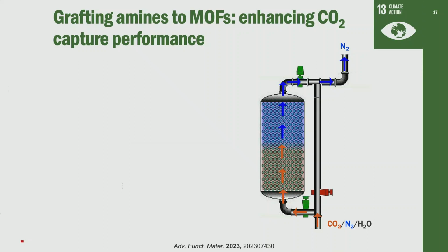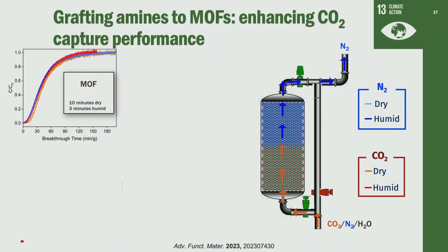The material will grab the CO2, and the first thing that comes out of the column is nitrogen. So we watch when the nitrogen comes out, then we watch when the CO2 comes out later. The difference is referred to as our breakthrough time, the difference in those 2 time points. So here, this is what you're seeing, is the actual breakthrough. We see the nitrogen come out, and then later we see the CO2 come out, both in dry and humid